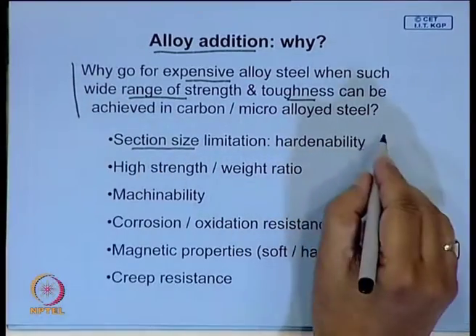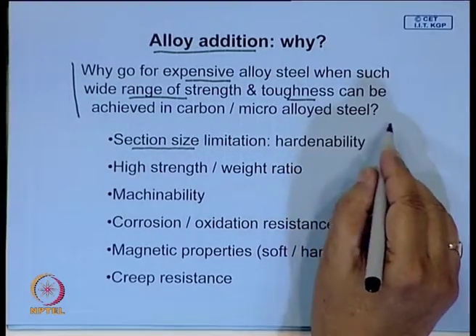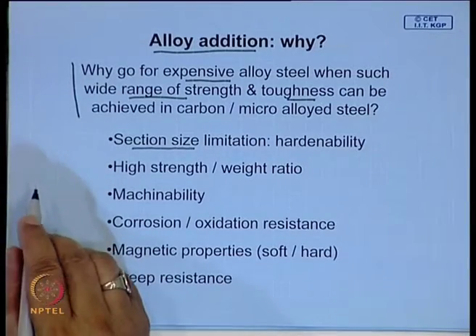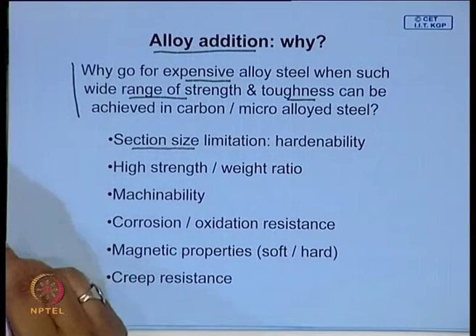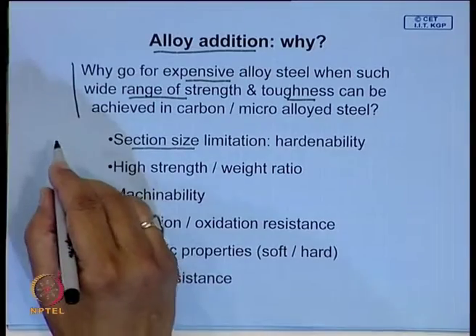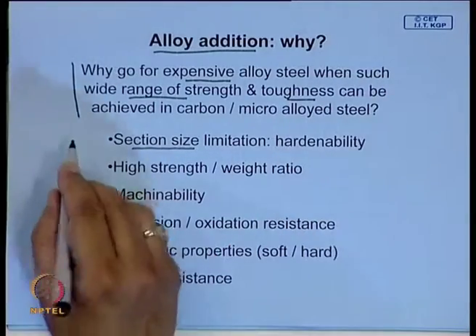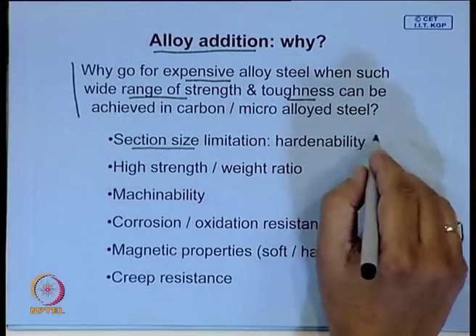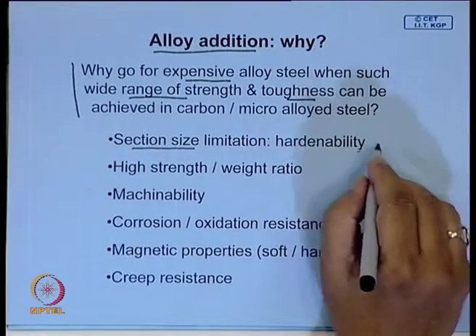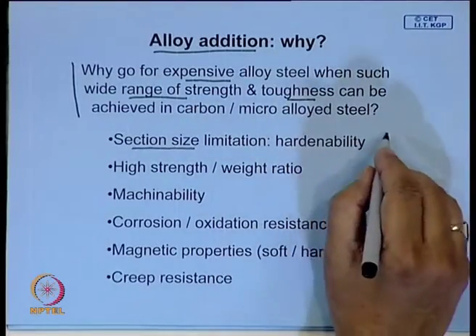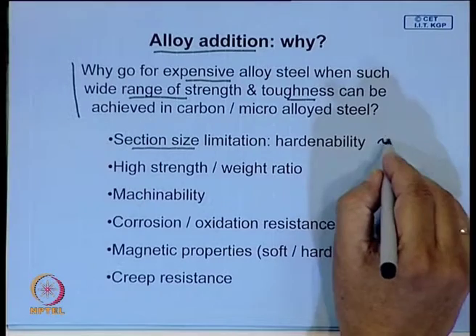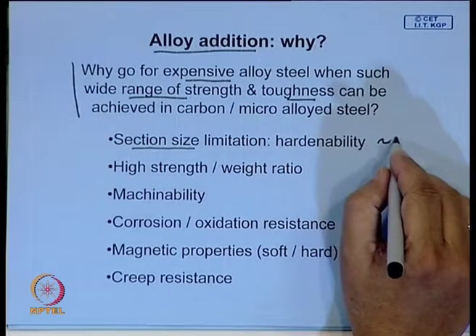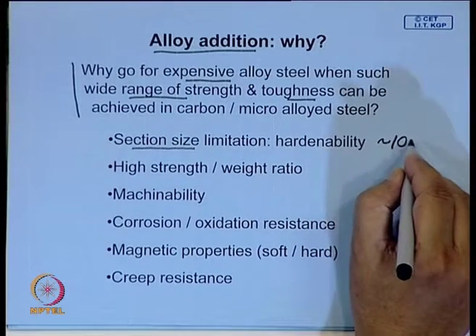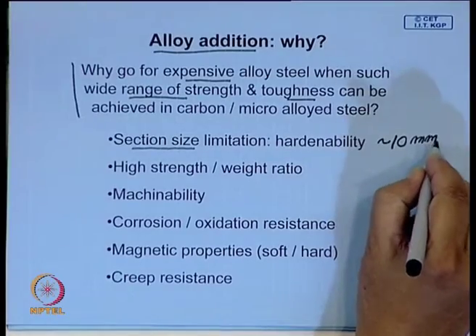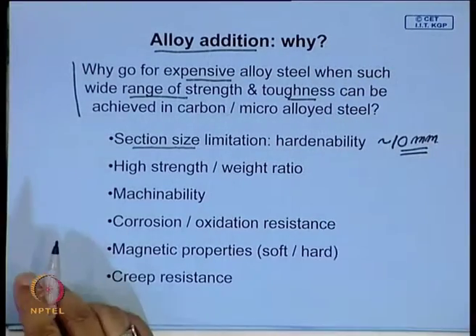Say plain carbon steel, even in the case of infinite quenching, say extremely high rate of quenching, ideal quenching, you may be able to get through thickness hardness, that means 50% martensite at the core, up to, depending on carbon content, maybe say 10 millimeter. So, in many applications this is too small.